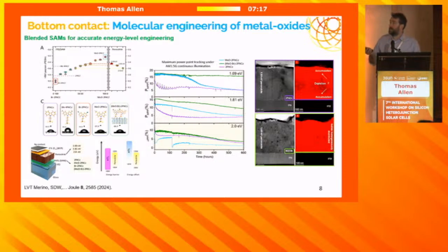With this, you can choose your respective SAM ratios to tune the valence band to match the valence band of different perovskites. Because usually when you're changing the band gap of the perovskite, the energy level that changes most is a deepening of the valence band. And so what Lewis showed is that when you tune the energy levels to match the energy levels of the perovskite for the contact of the valence band, in all of these situations, you get a higher efficiency, but you also avoid halide segregation, or at least suppress the rate of halide segregation in the perovskite bulk.